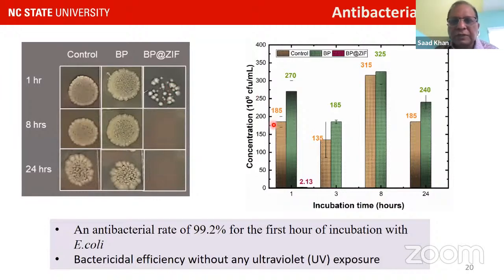That's shown here more quantitatively. This is after 1 hour, you can see very little bacteria left, and after 3, 8, and 24 hours, there's hardly any there. So 99% of the bacteria are gone in the first hour. Now, I should point out that there is work done using MOF with a substrate for antibacterial, but many of these works use UV exposure, so we don't have to use that. So that's an advantage there as well.